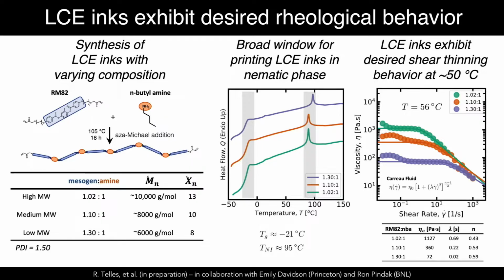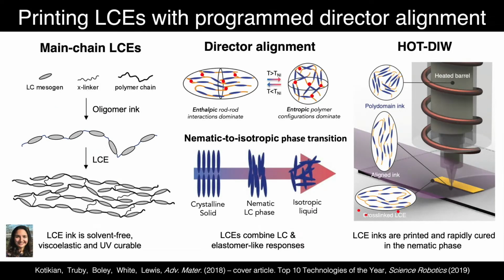These are fairly high molecular weight oligomers, 10,000 grams per mole. If we look at the differential scanning calorimetry data, we see a pretty large range of temperatures where we could work for printing, above the glass transition temperature and below this T_NI value, which for these materials is around 95 degrees C for what I'm going to show first. Then we can take this data and fit it to a Carreau fluid model, and we can get the characteristic relaxation time lambda here, which becomes important. I'm going to describe that in the next slide. And you can see that this is all done at elevated temperature, so we have coined the term hot direct ink writing. Let me go back here. This is actually heated.